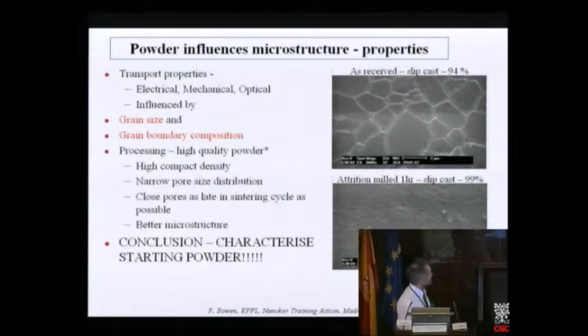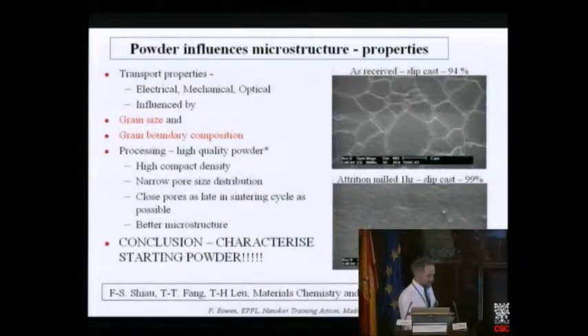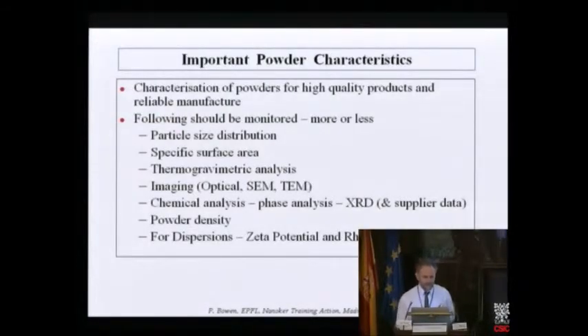The conclusion is, we need to characterize the powders at the beginning, and you need to do it well. If you are having problems with sintering, you probably don't have a sintering problem. You probably have a powder problem, and you need to characterize correctly at the beginning. This is excellent work which shows this particularly in detail.